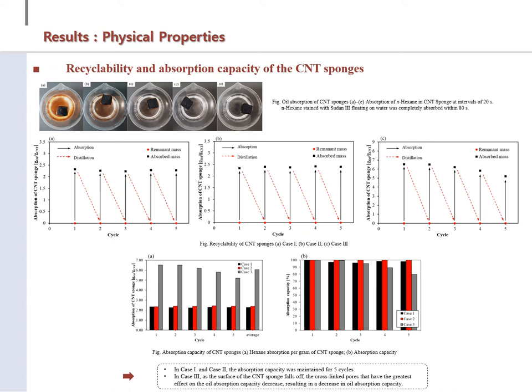Finally, recyclability of the absorbent was carried out. Cases 1 and 2 showed similar oil absorption ability with the increase of the number of reuses, up to 5 recycles of oil absorption and desorption by distillation method.